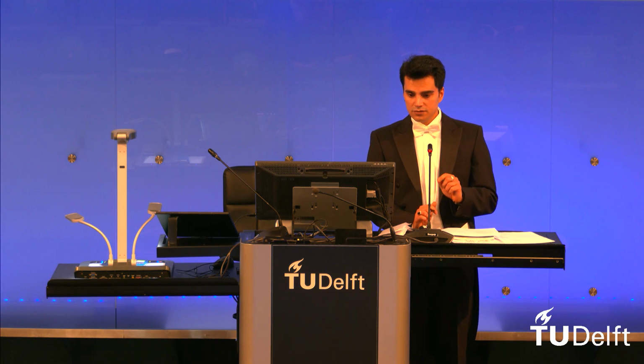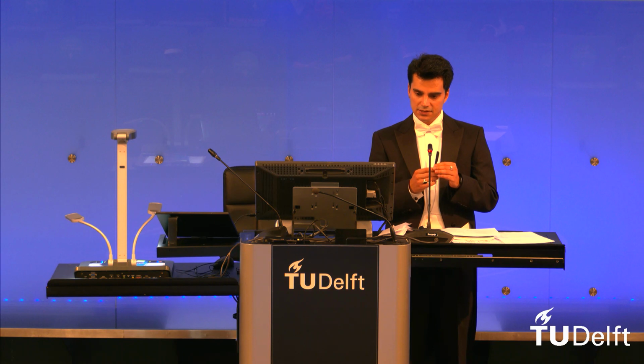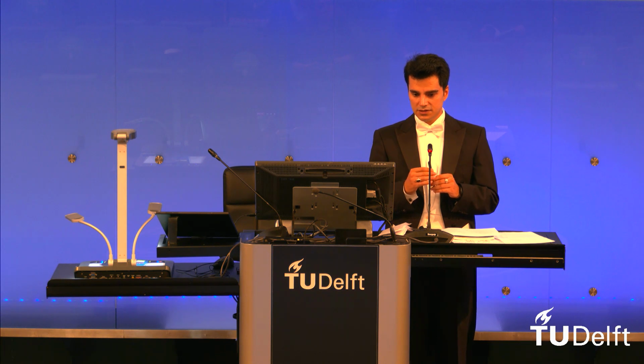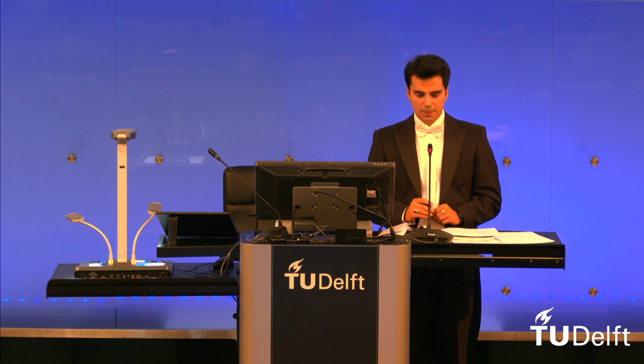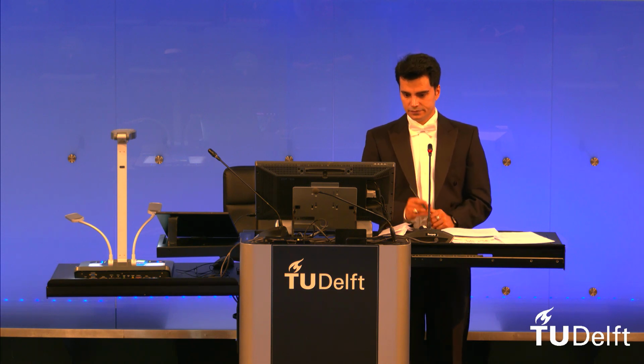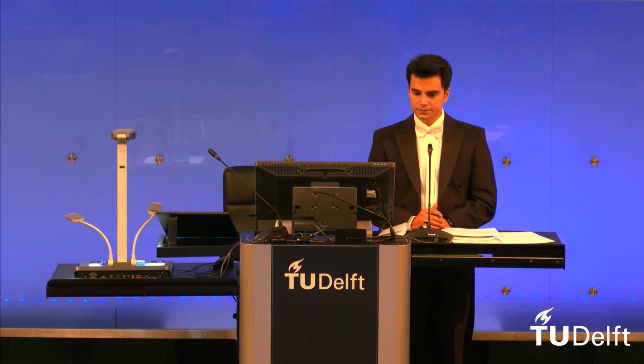And I would also like to add one more thing about the rotation, because the sample is rotated 360 degrees around the pivot axis, by which you can gather the results step by step, and you can detect the final morphology of the cracks at the detector site. And the steps for rotations, I guess it would be in the range of 0.1 degree at each step.